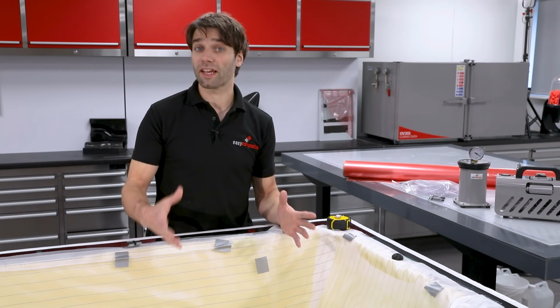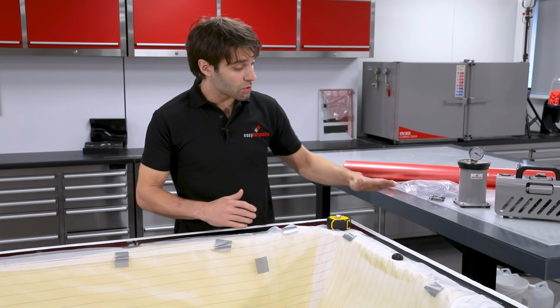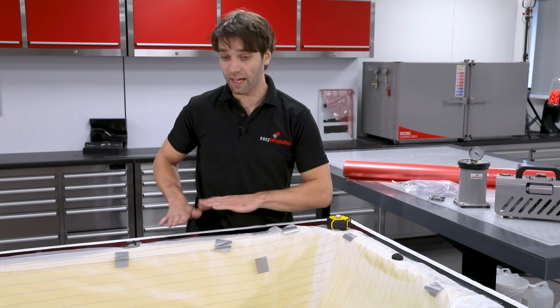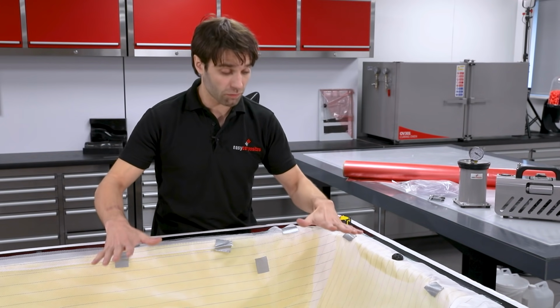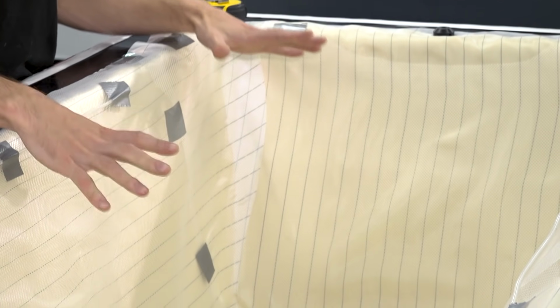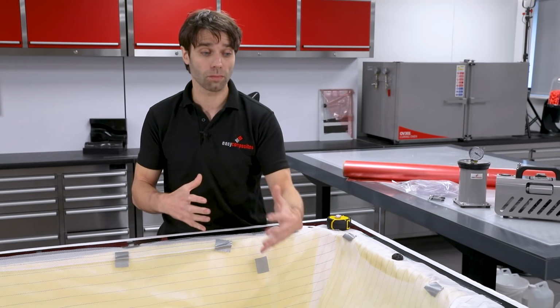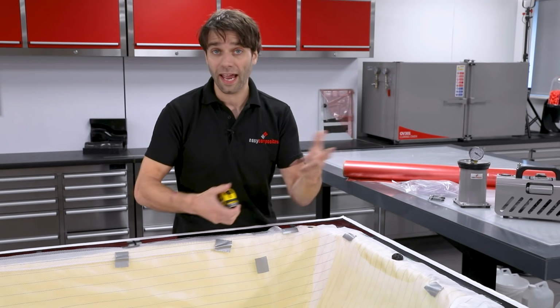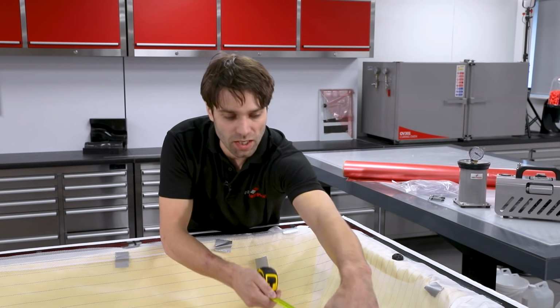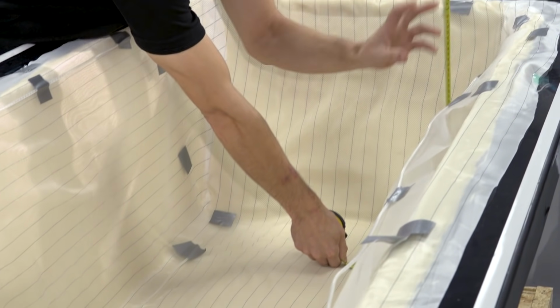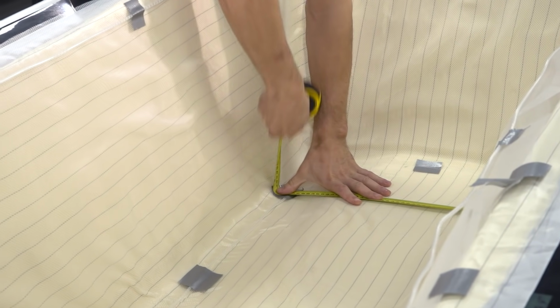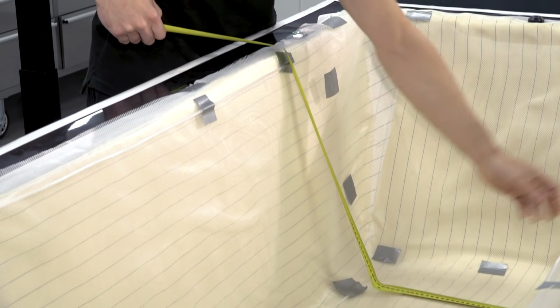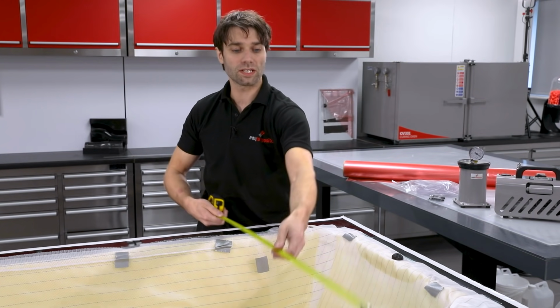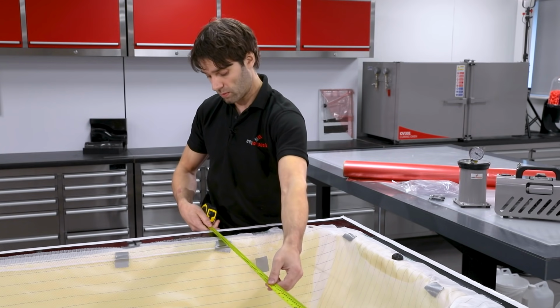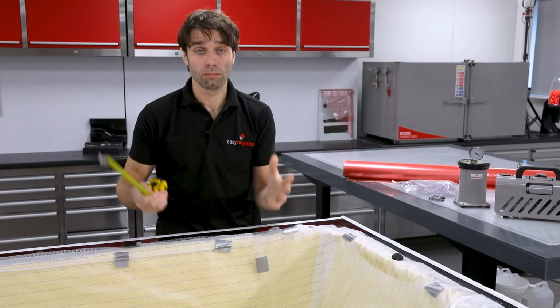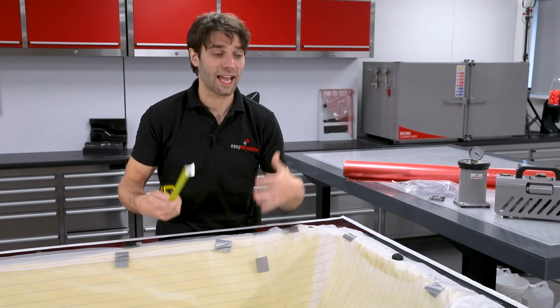We're now ready to go on with the vacuum bag itself. Now, clearly, if we were to just stick the vacuum bag straight onto this sealant tape and bridge across here, we wouldn't have enough bag to stretch down and contact all of the contours of the mould. So we need to get that additional bag onto the part. So to work out how much additional bag we need, if we just measure across the surface of the mould here, we've got around about 1.8 metres, and then if we were to measure straight across, we have a metre. So we've got an additional 0.8 metres or 800 millimetres that we need to add into the bag.